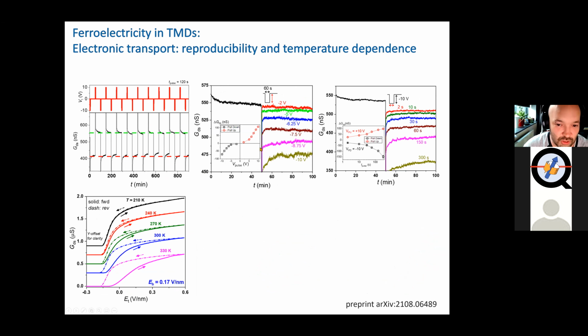There is an instant switching, meaning that there is a very quick sudden change in the domain structure, but then there is a trail, which is a long-term relaxation. So perhaps those impurities and little bubbles do pin the domain walls, which slowly over time relax into this new configuration. The switching is also helped by temperature. The higher the temperature, the better they switch, because phonons in the system promote the movement of the domain boundaries, domain walls, and they release the pinning.